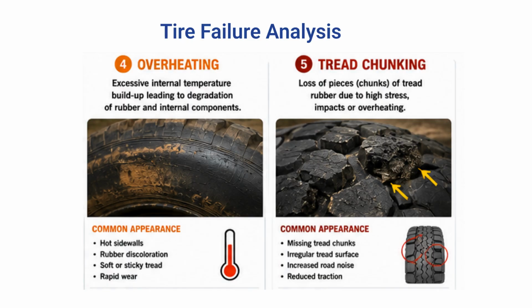Let us understand 2 more tyre failure modes: overheating and tread chunking. Overheating occurs when excessive internal temperature builds up and begins to degrade the rubber and internal tyre components. Typical warning signs include hot sidewalls, rubber discoloration, a soft or sticky tread surface, and unusually rapid wear. The most common causes are underinflation, overloading, high-speed operation, and high ambient temperature.